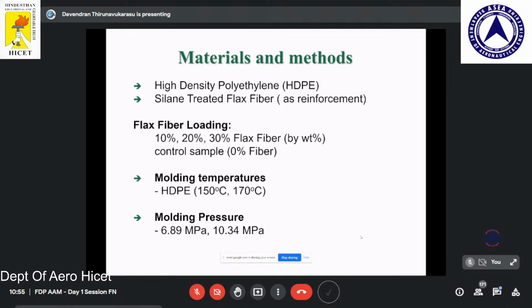And the fiber is silane treated, because silane treatment can improve the coupling. That means silane is a coupling agent. We can get good adhesion between the polymer and the fiber, so it improves the fiber interface properties.